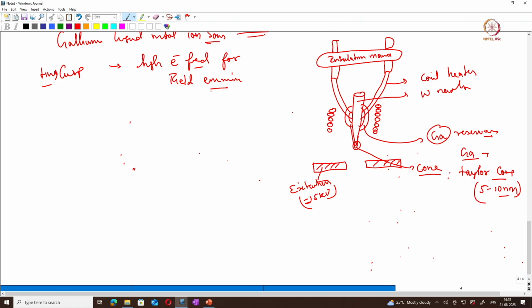Now I hope you must be thinking about the atom probe. In your atom probe, the needle is kept at positive voltage. There is an electrode which is kept at a negative voltage, and due to the application of DC voltage, what will happen? The atoms on the tip surface get polarized and get ionized. They become positively charged, and these positive ions are accelerated along the field lines towards the negative bias, correct? This is a similar concept to that used in the focused ion beam.